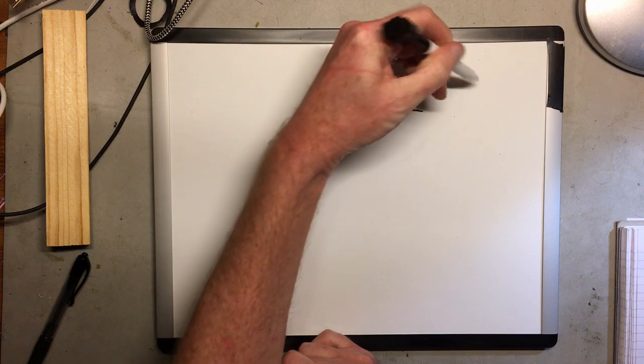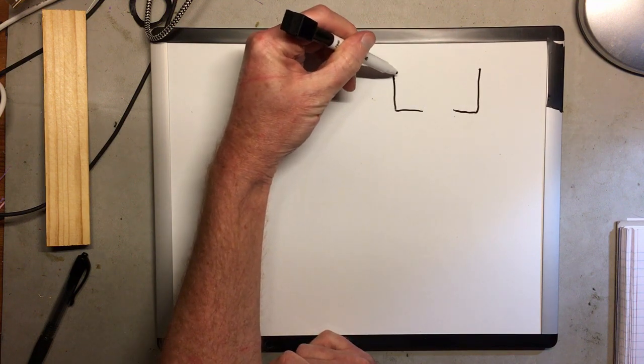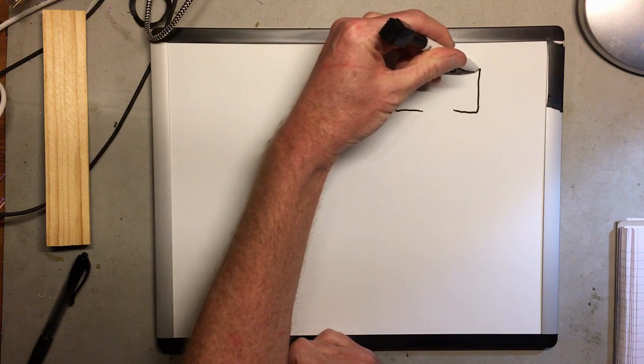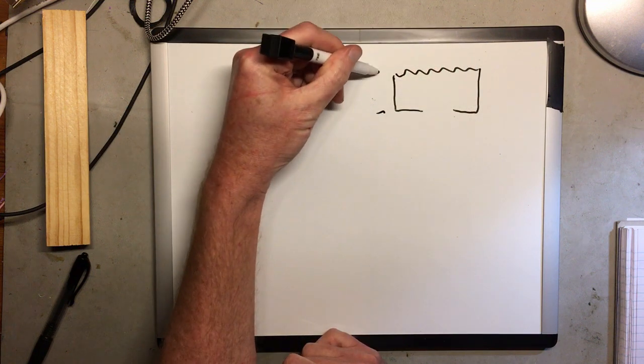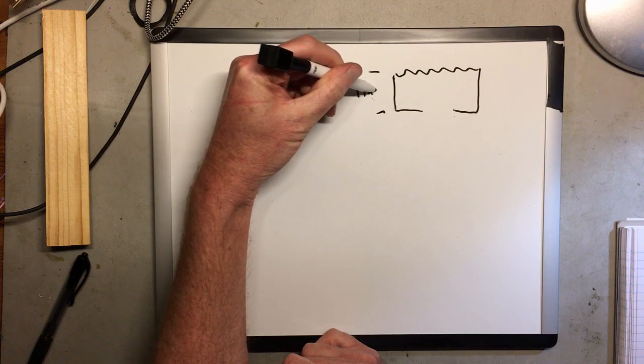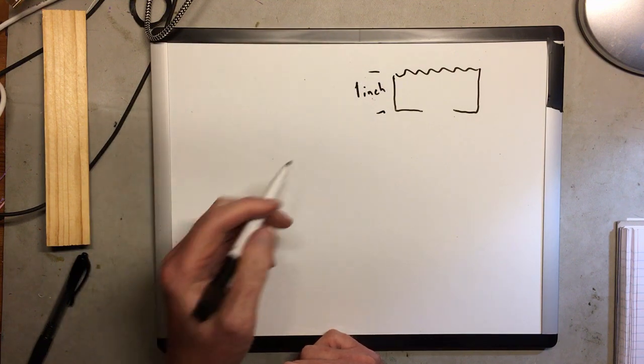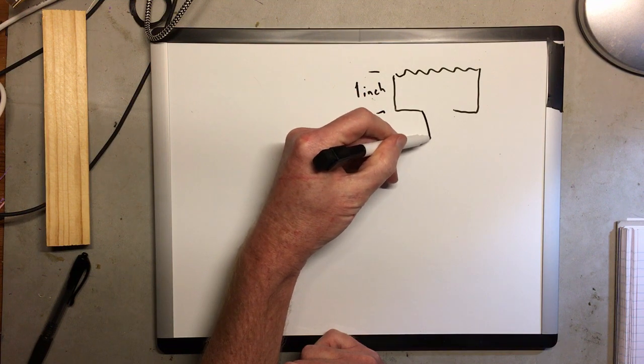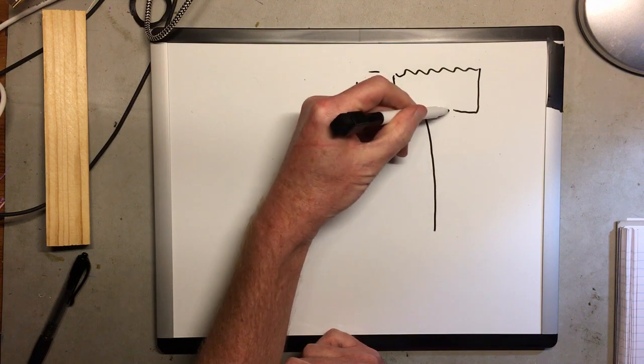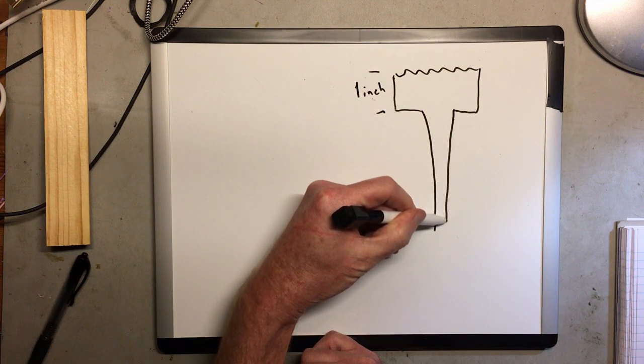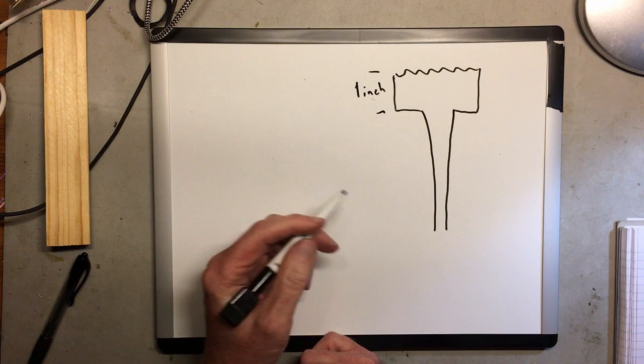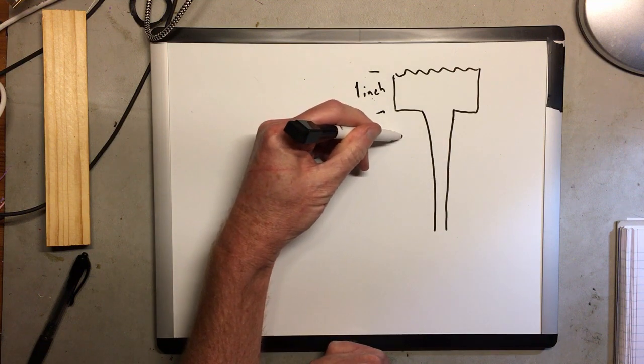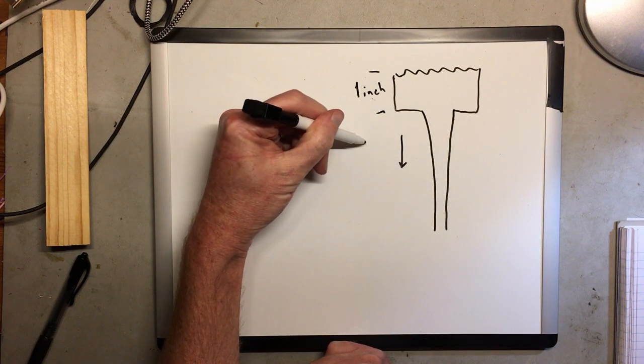The first principle of a naturally pressurized running system is that the flow of metal is constrained until it enters the mold cavity. Like everything else, a stream of molten metal accelerates as it falls. So if we have a pouring basin that is one inch deep and we want 10 cubic inches per second to flow out of it, then we can calculate the speed of the falling metal when it leaves the bottom of the basin and at different points as it continues to fall.